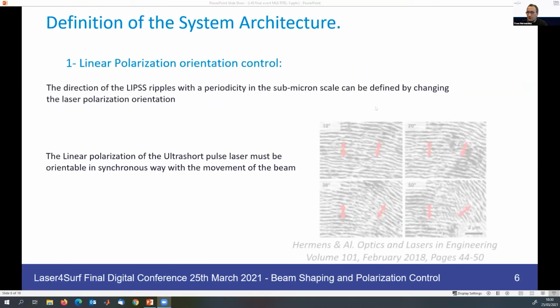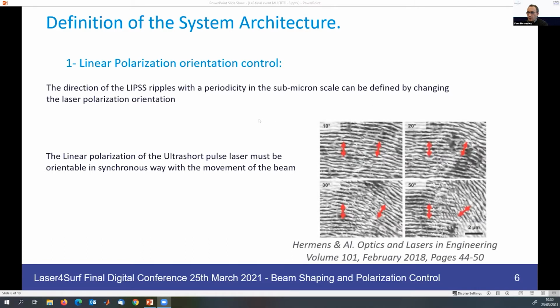The linear polarization orientation control is useful in order to decide the way you want the LIPSS to appear along your beam traveling on the sample. So we have a linear polarization from our ultra-short pulse laser, and we want to orient it ideally in a synchronous way with the movements of the beam. So it has to be synchronized with the scanner mainly. You can see from this example from literature the impact of the orientation of the polarization on the patterns realized by LIPSS.